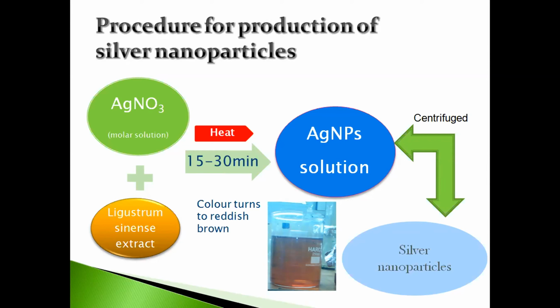Because when we are taking the extract out of green leaves, the solution is mostly green, because silver nitrate doesn't have any color. It is transparent, and the extract has green color. But when we add them, the silver ions turn to silver metal nanoparticles. They turn reddish brown. The color turns to brown, and it signifies that there is synthesis of silver nanoparticles. And after the synthesis, as you can see in one beaker, there is that reddish brown solution. We can get the solid nanoparticles through centrifuging the solution, and then taking that residue and heating it afterwards.